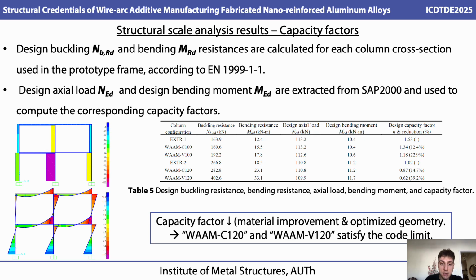As you can see, the first sections, the small sections featuring 100 mm external dimensions, do not satisfy the limit of 1, which is the capacity factor. However, when we use the larger sections featuring the 120 mm external dimensions, the extruded section still does not satisfy the limit. However, both of the WAM sections, the constant thickness and the variable thickness, satisfy the limit of Eurocode 9. And for the last section, the WAM V120, we conclude that it may be used for additional loading or the construction of an additional story.